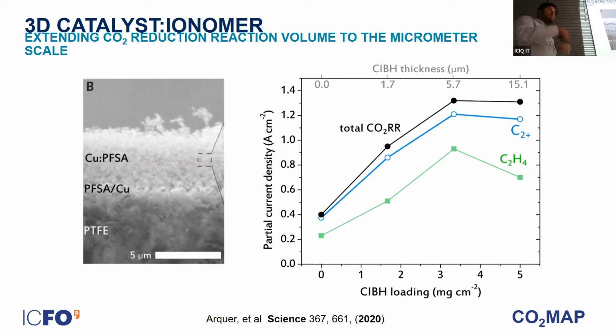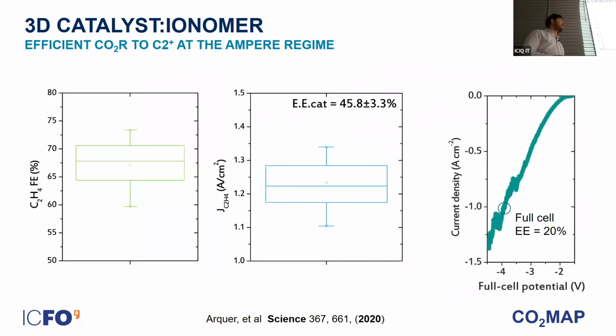So then we went to optimize more things in the system, such as the exact electrolyte composition, the exact thickness, and we obtained an overall combination of figures of merit such as this. So the Faraday efficiency for ethylene was close to 70%. The total partial current density for ethylene was around 1.2 to 1.3 amperes per square centimeter. So this is much higher than before. And the half cell energy efficiency for this reaction was around 45%. But when you measure the full cell reaction efficiency at 1 ampere, we were obtaining around 20%